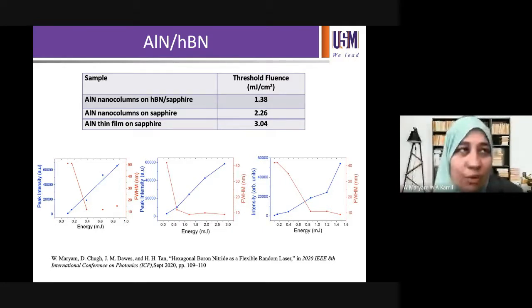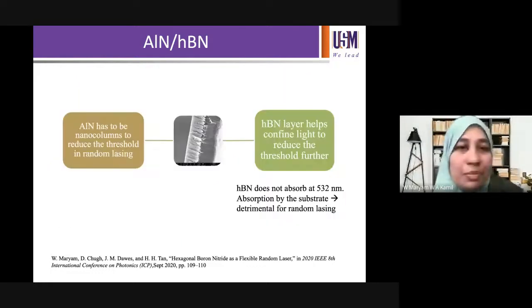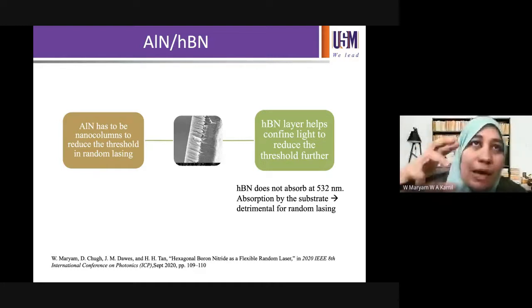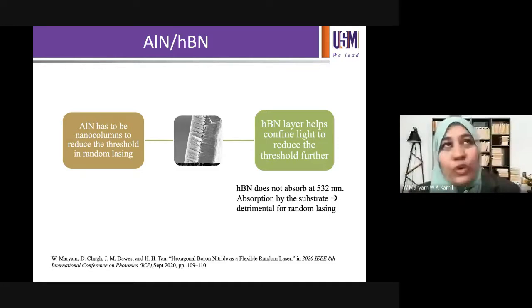So it's apparent you need nanostructure. It's apparent that you may actually need nanorods or nanocolumns, and it was also apparent that HBN played a particular specific role. And I think it's because hexagonal boron nitride does not absorb at 532, which was the pump source. So this means that there are more photons that are participating in the random lasing rather than in the absorption. So it's very important that you minimize the absorption of your substrate.